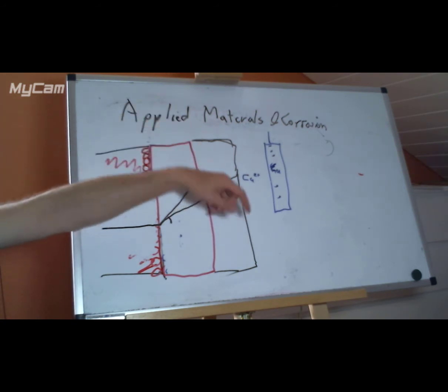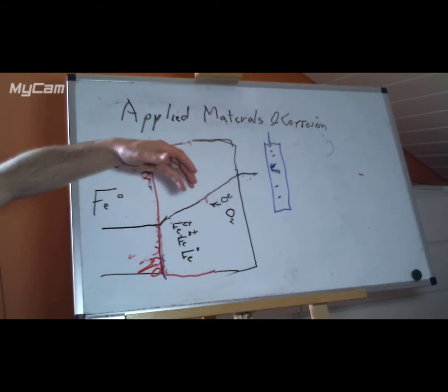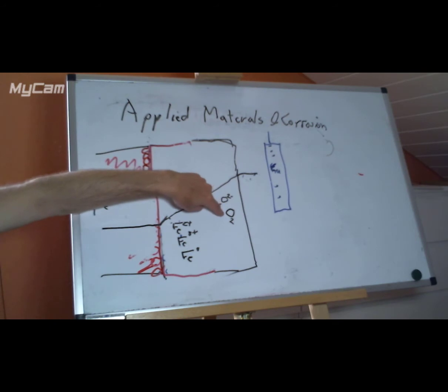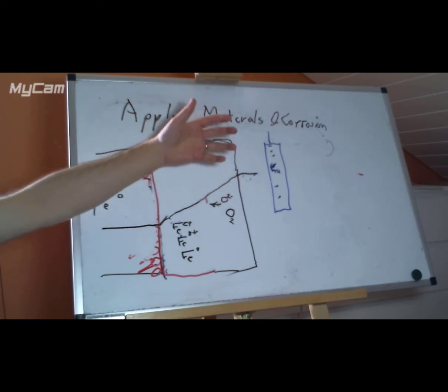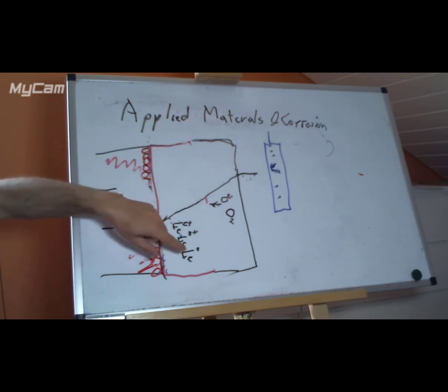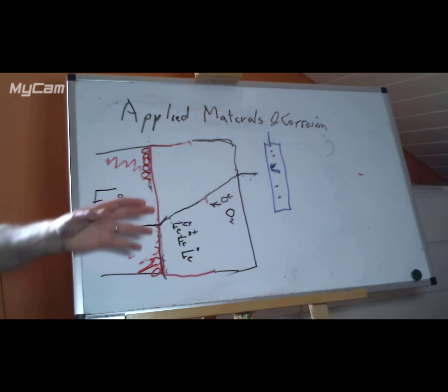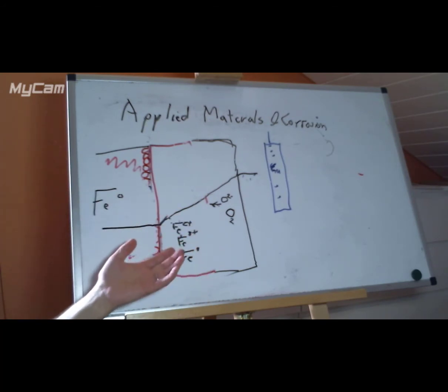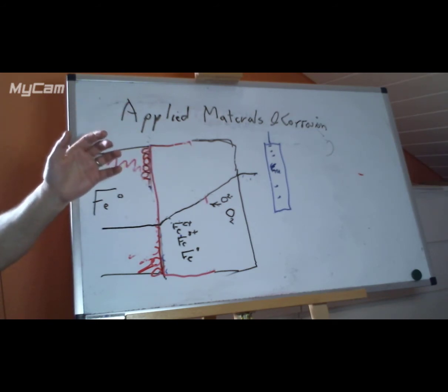Depending on what we have on the outside, it might not be oxygen. But what species are going to move inside this? We can imagine there's a possibility that molecular oxygen could make it through. It's relatively big, so it's comparatively unlikely, but if it was a small atom, it might be able to get through. We can imagine that iron 0 could make its way through. We can imagine that iron 2+ or iron 3+ could be trying to move through, because they vary in size and they vary in oxidation potential. So maybe we should think about what the oxidation potential is going to be.